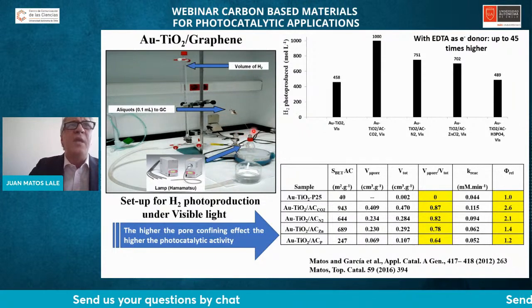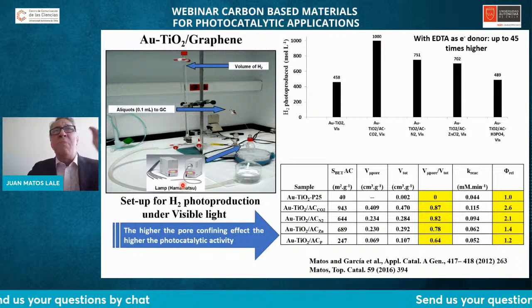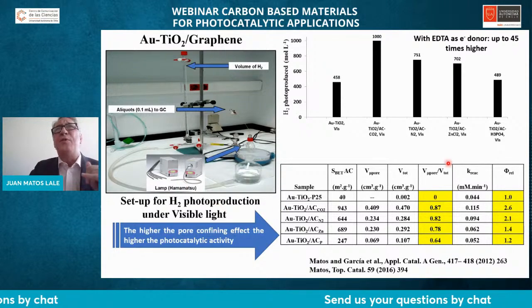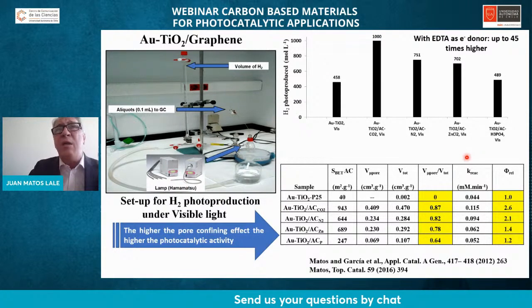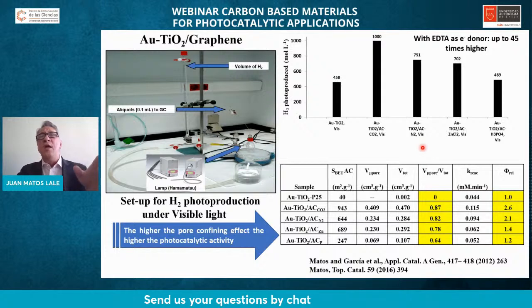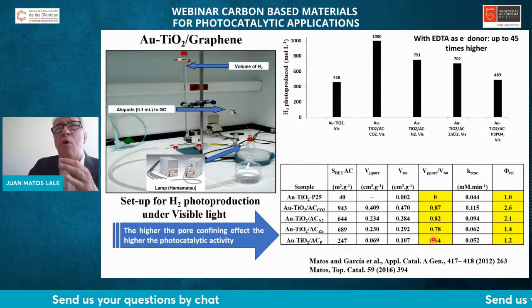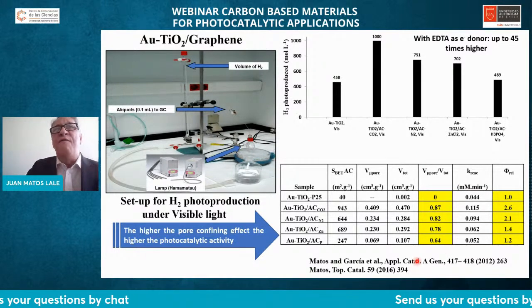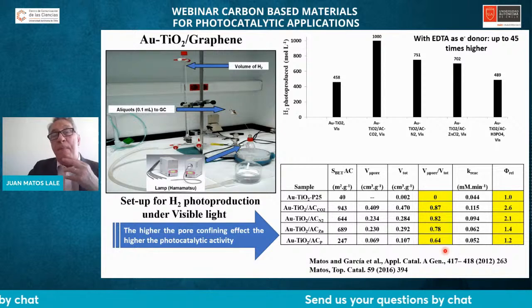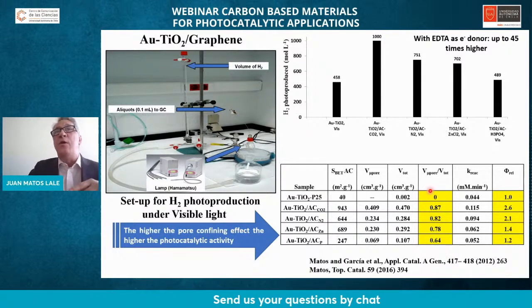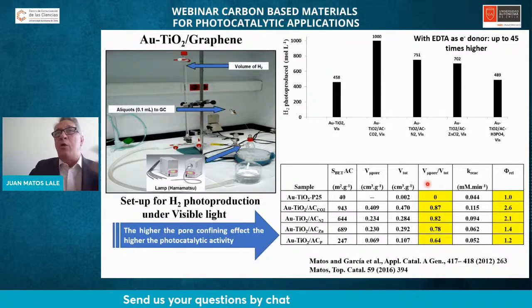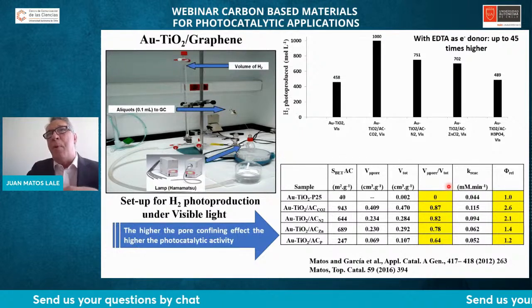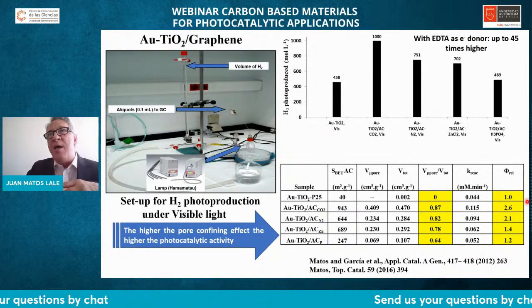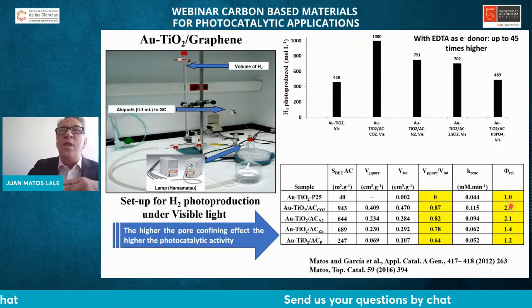In a very simple reactor with a Hamamatsu fiber optic, we are able to produce hydrogen in very high quantities. At the same time, we achieved a correlation between the confining pore effect, estimated by the ratio between the micropore volume and the total pore volume of the carbon, and the quantum efficiency.